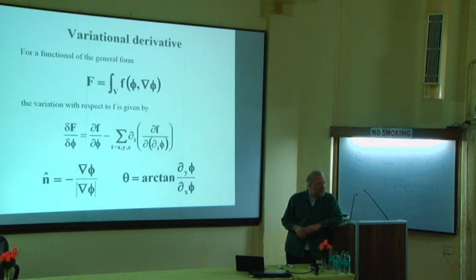And this is maybe not always very much appreciated, but this fact is one of the major advantages of phase field models with respect to level set methods, for example, because here this physics is automatically incorporated, and you never need to evaluate things like curvatures, directional derivatives, or things which you would need to do in the level set method, where you have to program this Gibbs-Thomson boundary condition by hand. Okay?